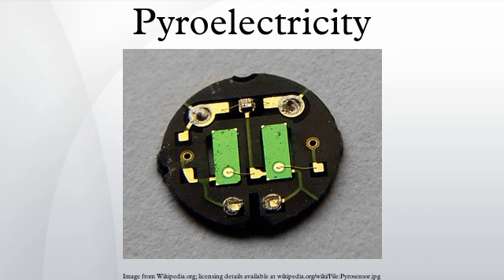All crystal structures can be divided into 32 crystal classes, according to the number of rotational axes and reflection planes they exhibit that leave the crystal structure unchanged. Of the 32 crystal classes, 21 are non-centrosymmetric. Of these 21, 20 exhibit direct piezoelectricity, the remaining one being the cubic class 432. Ten of these 20 piezoelectric classes are polar — they possess a spontaneous polarization, having a dipole in their unit cell, and exhibit pyroelectricity. If this dipole can be reversed by the application of an electric field, the material is said to be ferroelectric.